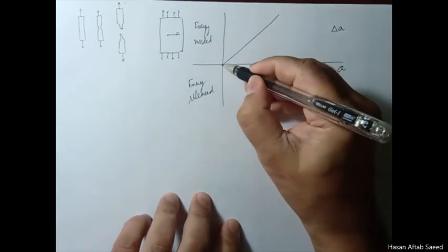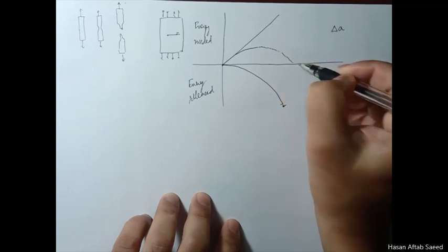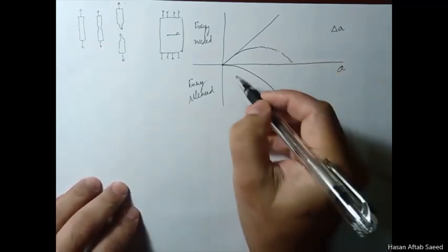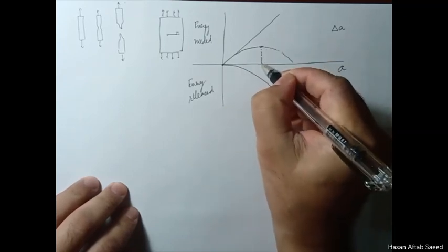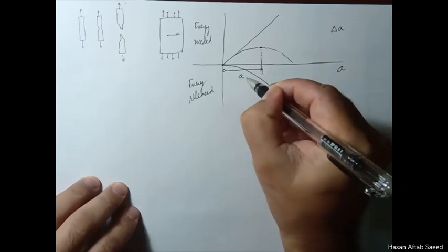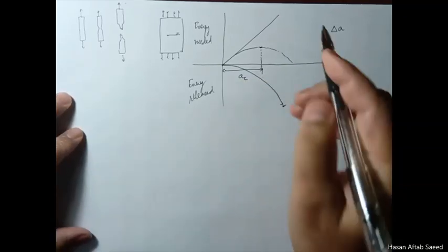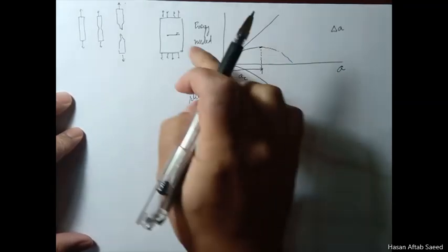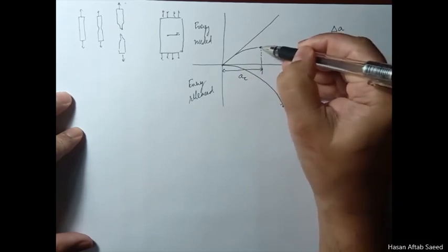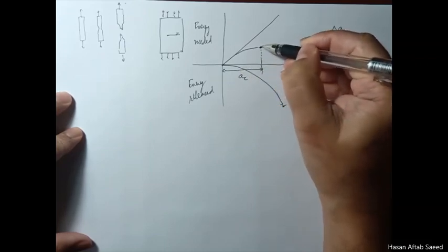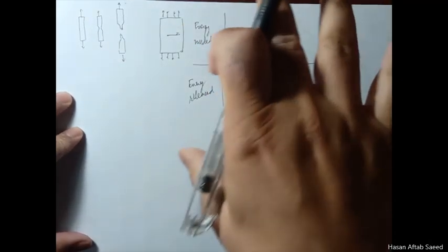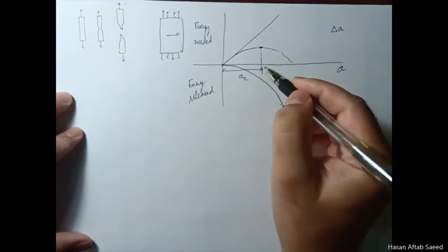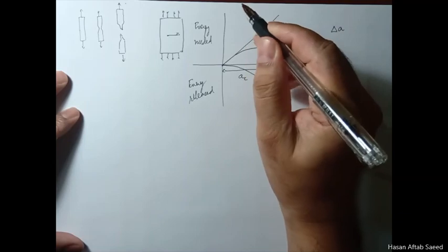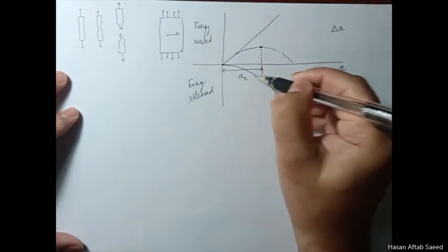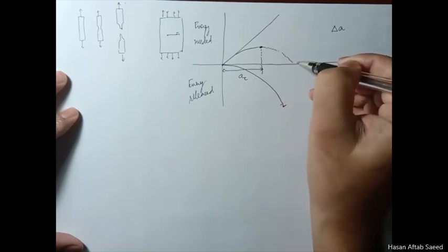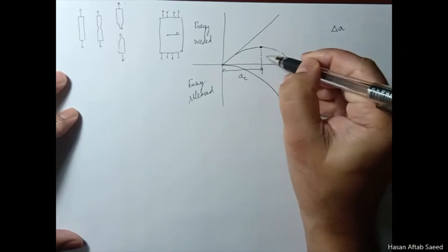If you superimpose the two, you get something like this, which shows you that for a certain crack length, which we'll call AC, the critical crack length, you need to put some work in order to extend the crack. But once you reach this point, or in other words, you have a crack length equal to or greater than the critical crack length for a particular stress level, for a different stress level the critical crack length will be different. For the stress under consideration, if you have a crack of length AC or more, then it's a spontaneous crack extension. You don't need extra work to increase the crack length.